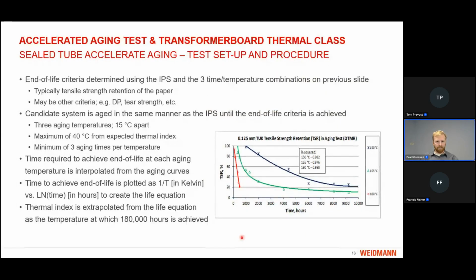So one of the first things to do when completing this standard or this test is to determine the end-of-life criteria of the system. We do that by using the industry-proven system at the 3 time-temperature combinations that I discussed 2 slides ago, along that minimum life expectancy curve. So the industry-proven system is aged, and then the tensile strength is tested following those aging periods, and that retained tensile strength is used as the end-of-life criteria for the candidate system.